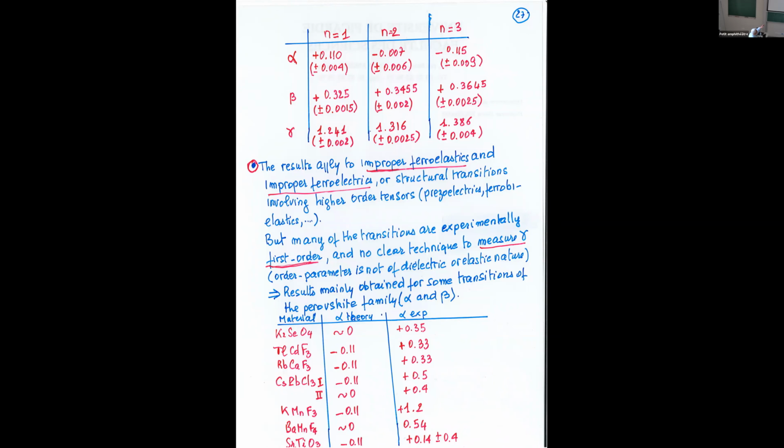And you see that for alpha, it's around 0, but it can be a bit more for a unidimensional order parameter, a bit less for n equal 2 or 3. Above 3, this argument of anisotropy erased by fluctuation doesn't work, so we remain only below 3. For beta, we see that it's smaller, and gamma is larger. This is the result.